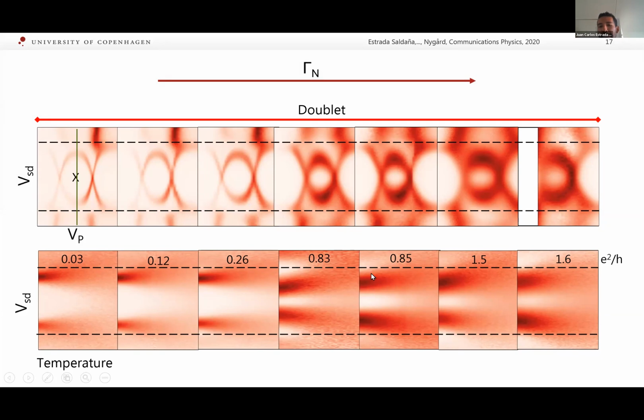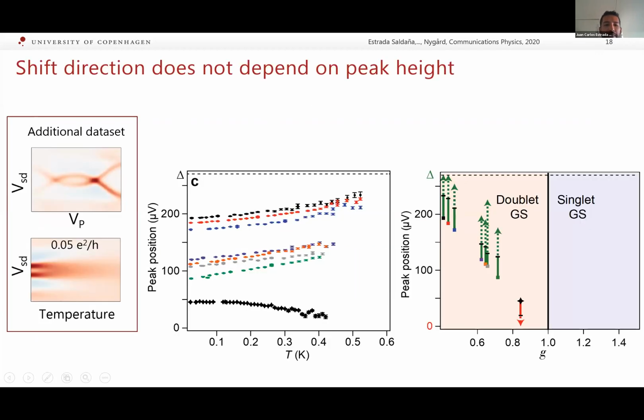So it seems that the height of the peak doesn't affect the shift too much. They still shift towards the gap. All of them are closer to delta, so they should do that. We add this additional set, which is measured close to zero bias, again in the same charge state. And because it's measured close to zero bias, as we learned from the previous data, it converges towards zero bias with temperature. It doesn't split. And we fit the YSR peaks as we did before, and we plot peak position versus temperature. And we find that peaks that are closer to the gap shift towards the gap, and the peak that was closer to zero bias shifts towards zero bias.